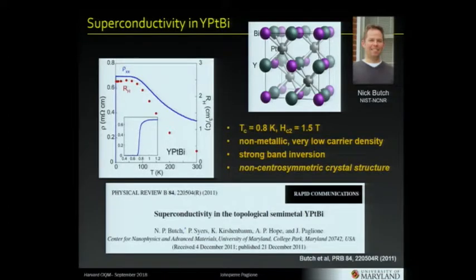This was Nick Butch. He was a postdoc at the time that did this work. TC is less than 1 Kelvin. HC2 is between 1 and 2 Tesla. The interesting things are that the carrier density is extremely low, on the order of 10^17 or 10^18 carriers per cubic centimeter. At the time, that was actually the lowest carrier density, but then we got usurped by some strontium titanate work that came shortly after. But anyway, it's very low. It actually remains not understood how you can have such a low carrier density system and have it become a superconductor.